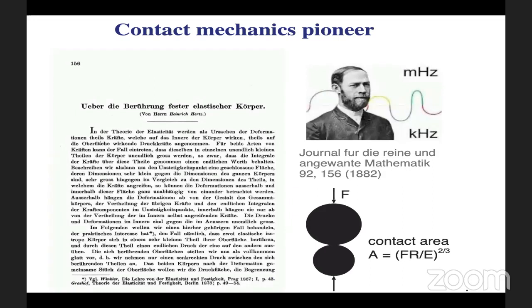Now I come to contact mechanics. Contact mechanics basically starts with Hertz. Hertz was known for his work in electromagnetism, but tribologists know him because he gave a relation between contact area and the force between two spheres which are squeezed together. According to Hertz, the area of real contact when two elastic spheres are squeezed together has a non-linear relationship: the area of real contact depends on the normal load to the power 2/3.